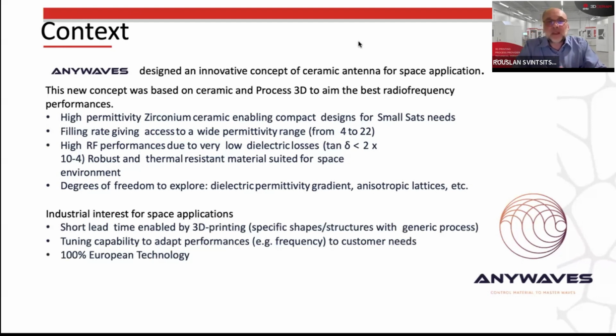So why did they choose additive manufacturing, and why zirconia? Zirconia is a material known for antenna applications because of its high permittivity, and we can print with two types of zirconia available in our standard portfolio. It's zirconia stabilized with 3% yttria and zirconia stabilized with 8% yttria, which is used for electronic applications. So this latter one was used for this antenna.